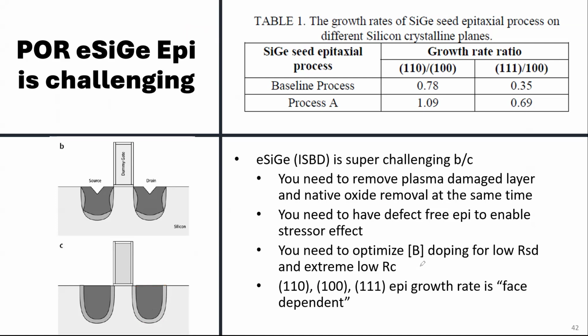And you need to optimize boron doping. So the doping here, the first layer should be very low doping, right? Why do you need low doping here? Because if you have high doping here, then when you heat up, the dopant will come into the channel. So you lose your channel control. Your LG is no longer what you defined. And this part is called the extension, right? EXT, the source drain extension, SDE. Source drain extension is very hard to engineer.